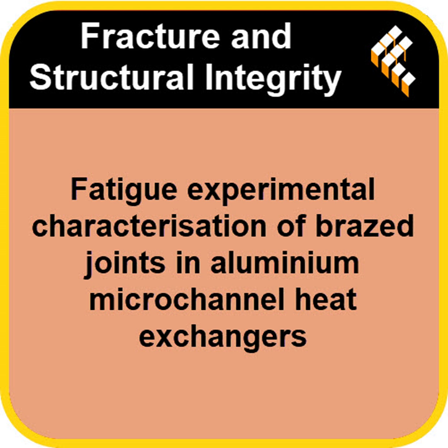Finding those right at the crack initiation site really underlines the absolutely critical influence of strict quality control during the brazing process itself. It means just perfecting the alloy chemistry or the overall component design isn't enough, is it? If the actual process of joining the parts together isn't clean and well controlled. It can undermine everything else. Absolutely. Achieving good fatigue performance, especially in these high cycle applications where things run for years, demands obsessive control over the entire brazing operation. From surface preparation to flux application, heating, cooling, everything.